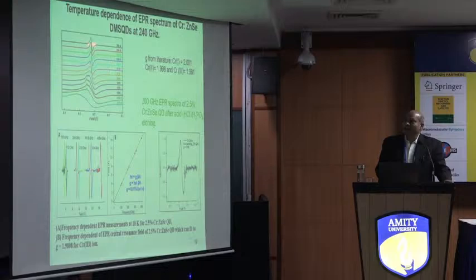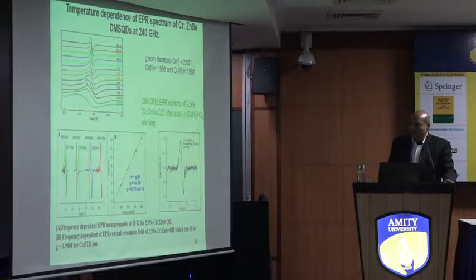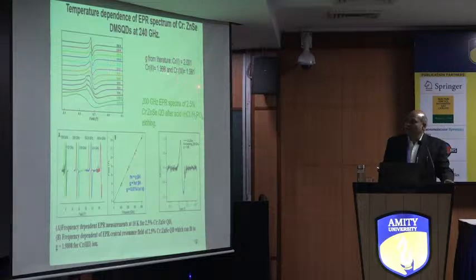Here what will happen? This peak is widening due to the chromium interaction and antiferromagnetic interaction coming here. And this is the EPR at different frequencies and a fixed temperature of 10K. Then we are able to calculate the G factor. If you see, the G factor is coming 1.9808. If you see the literature, this is chromium 3, again this is the confirmation.